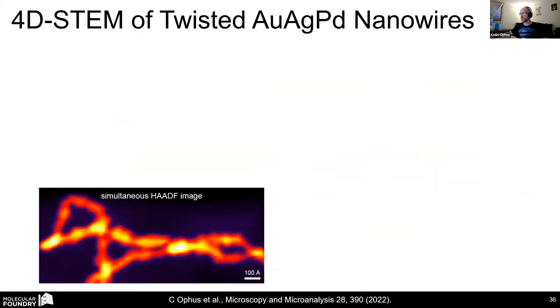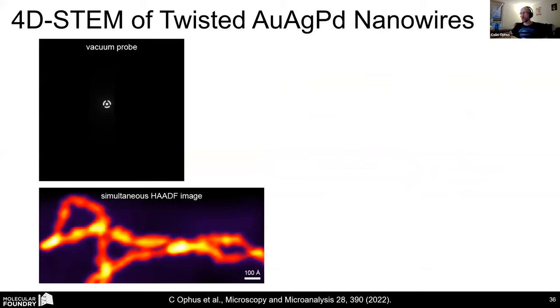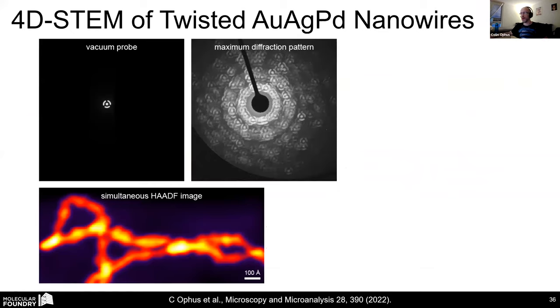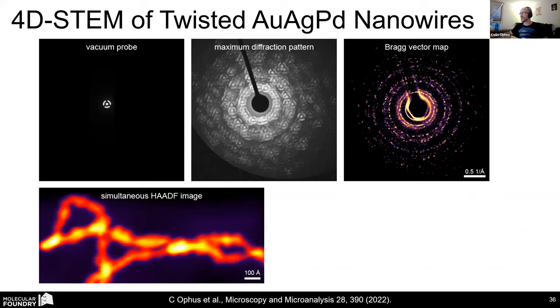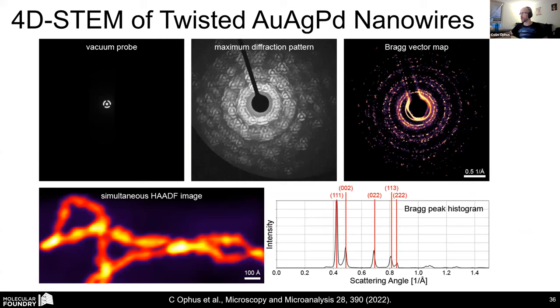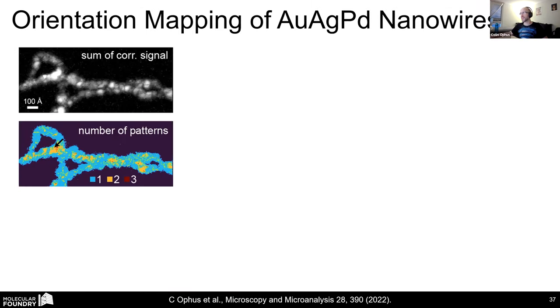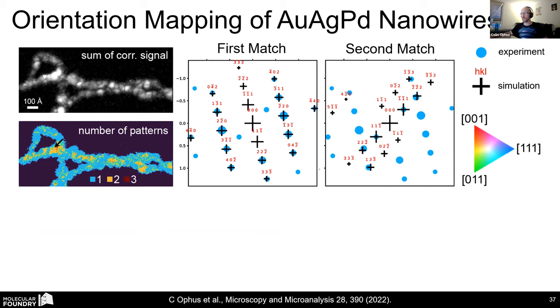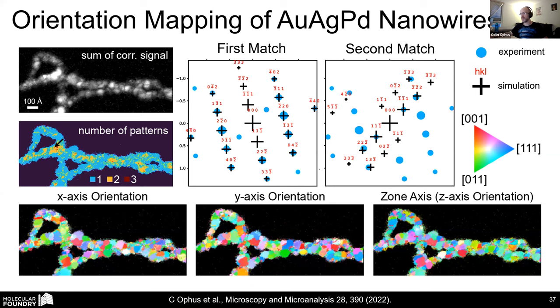So, one last materials science example: orientation mapping. We stamp bullseye probes into our patterned electron apertures here in order to more easily measure the diffraction pattern positions with high precision. This is a gold silver palladium nanowire, and this is all the diffracted spots scanning over the whole field of view. After the elliptic calibration I mentioned, we've written this crystal orientation mapping code in py4DSTEM to essentially fingerprint all of those diffraction patterns and determine the most probable, or second most probable, or third most probable orientation, and then do orientation mapping in a 4D-STEM experiment here.